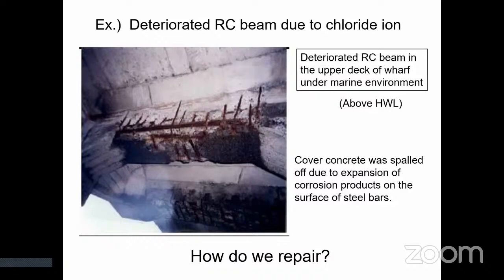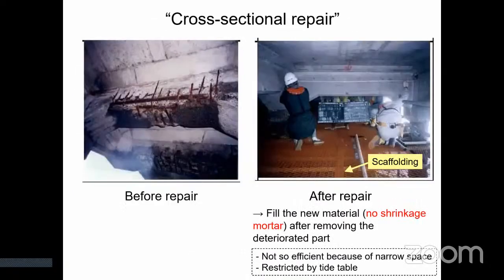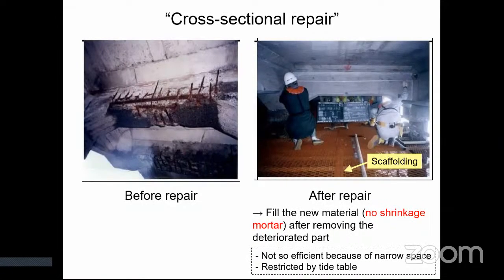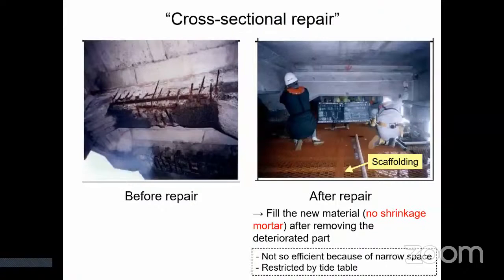In this case, how do we repair? In this case, cross-sectional repair method is applicable. New materials, such as non-shrinkage mortar, are filled after removing the deteriorated part. This work is conducted on the scaffolding. This space is very narrow, therefore, this work is not so efficient. Also, in some cases, workable time is restricted by tidal table.